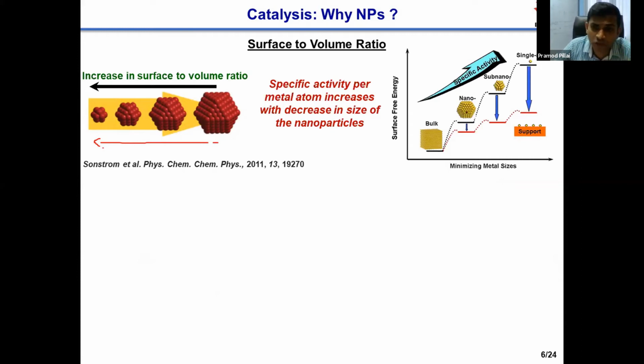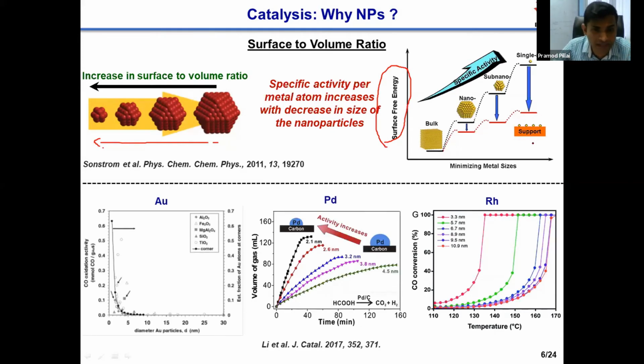The second reason is that when you reduce the size from bulk to a single atom, you increase the surface free energy of these atoms, which again can have a positive impact on their catalytic properties. And this was experimentally proved maybe 20 years ago. This is one example where people studied the effect of the size of gold nanoparticles on the catalytic oxidation of carbon monoxide. As you reduce the size of the nanoparticle, the catalytic efficiency increases. Similarly, this has been extended to other nanoparticles as well, for example, palladium nanoparticles. Along with improving the rate, the catalyst can also help in reducing the temperature at which a reaction occurs. This is an example where, when you reduce the size of a rhodium nanoparticle, you can perform the catalysis at a much lower temperature compared to a bigger nanoparticle.